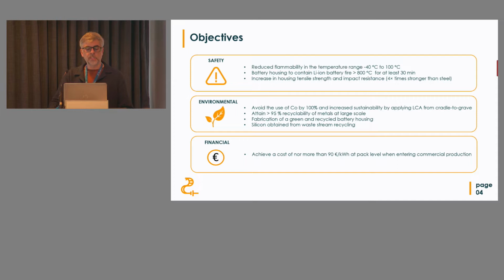And all of this is going to be complemented, which is the main point of the project, by getting rid of cobalt completely from the battery itself, using a life cycle assessment right from the beginning, from the materials and the components, to attain 95% recyclability of the metals, fabrication of green and recycled battery housing, together with the silicon materials that we are using for the anodes being recycled silicon from waste streams. Finally, the financial objective, which is shared with all the LC BAT5 cluster, is to reach 90 euros per kilowatt hour for the battery pack.